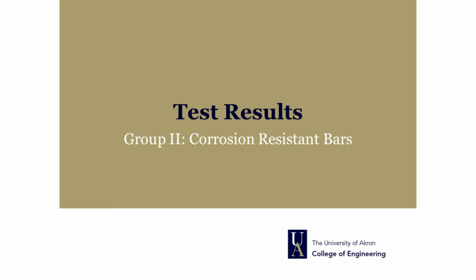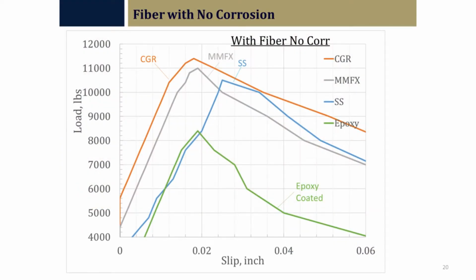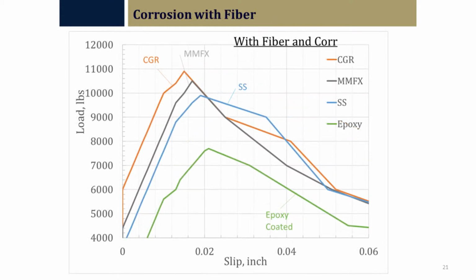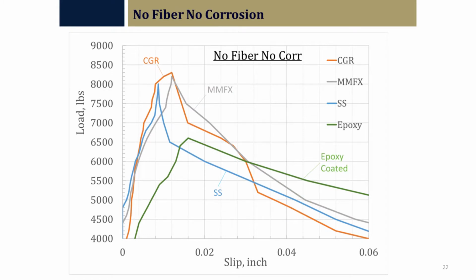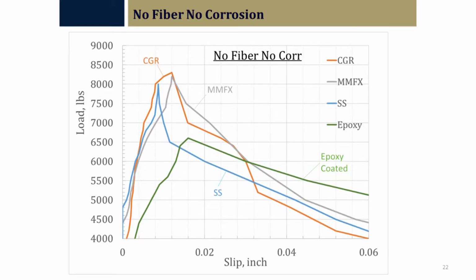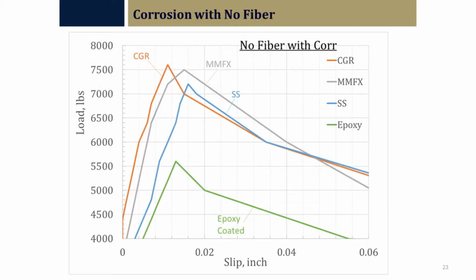Now, grouping these slightly different because those get a little blurry there. You can see what we're calling corrosion resistant, separation from epoxy. This is with fiber and corrosion. Again, a pretty good separation. No fiber and no corrosion, which would be your standard bridge everywhere, basically without the additional fibers, is high and to the left for the three over top of epoxy. Corrosion, similar result, but a lot less load over the slip there.